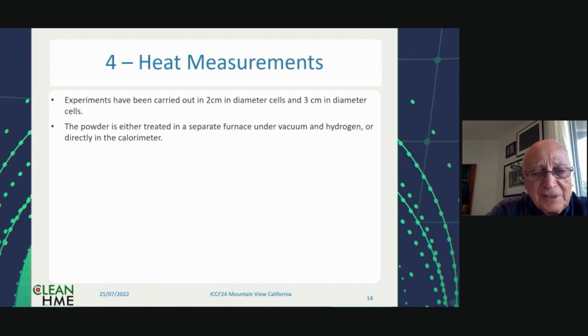So the experiments have been done in these 2 centimeter diameter cells and 3 centimeter diameter cells. The powder can be treated in a separate furnace beforehand, or in the reactor itself. The problem with doing it in the reactor itself is that the initial powder is very, very light, and when you use the vacuum pumps, the powder is pumped out, as well as the remaining air. So it's better to prepare it outside and put it in the reactor later on. Okay, next slide, please.